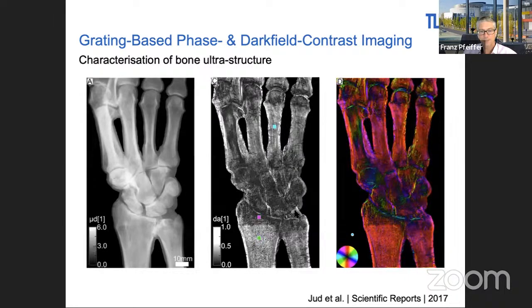Interesting is that we can study the ultrastructural alignment of bones. For example, this is a conventional bone image, so attenuation, and this is what we call the anisotropy image. You see that there's a region that appears much darker than this part of the bone. And this is now actually depicting the anisotropy.